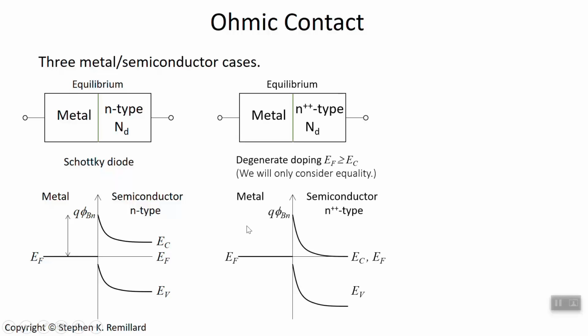Now let's increase that doping, and let's increase it a lot so that it is degenerately doped. Degenerate doping means that you've doped the semiconductor so much that the Fermi energy crashes into a band edge, in this case the conduction band edge, because it's n-type. We dope the semiconductor such that the Fermi energy and the conduction band energy are equal in the bulk, that they come to the same place in the bulk. But you still have band bending near the interface, and so the bands still bend upward, by the Schottky barrier height.